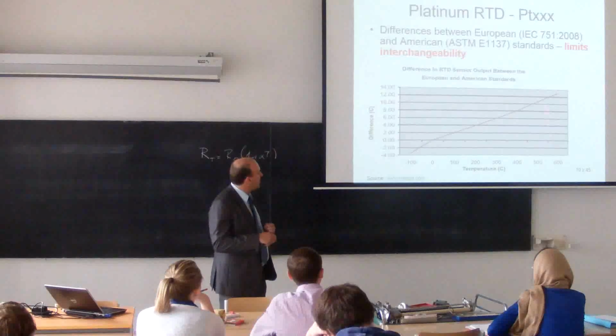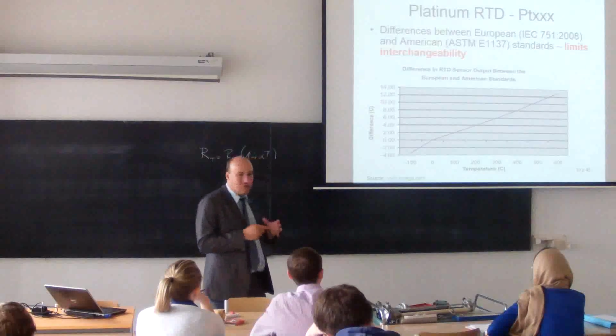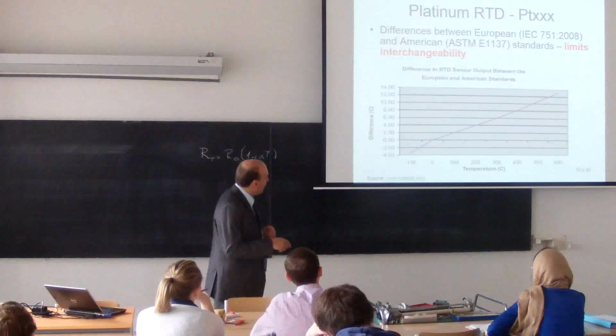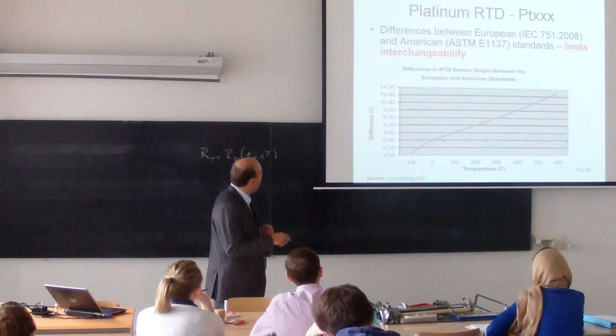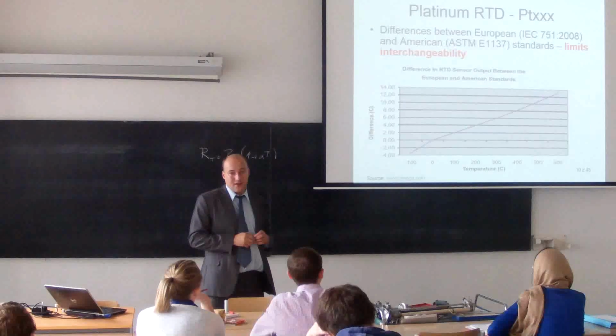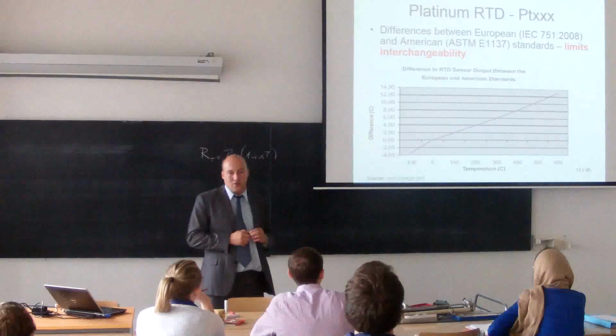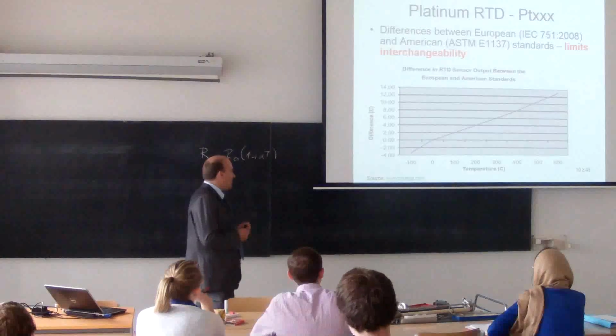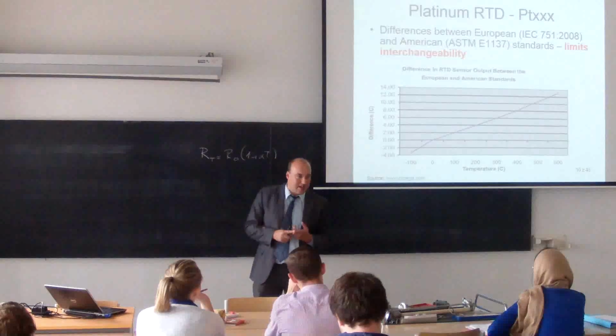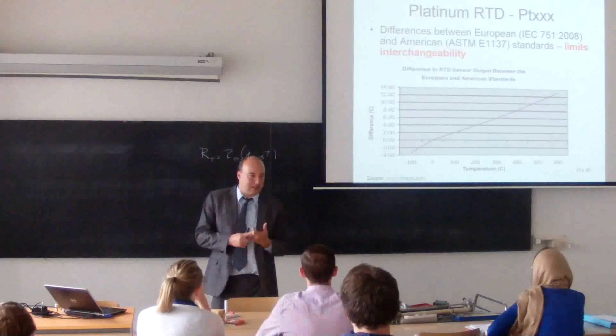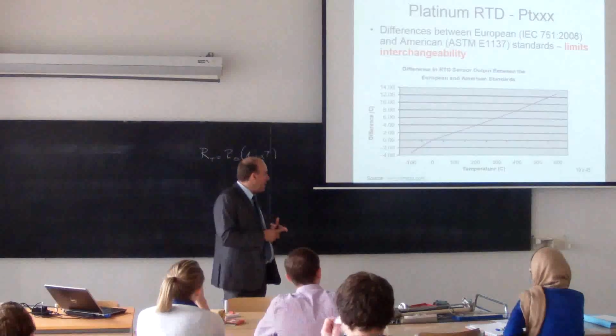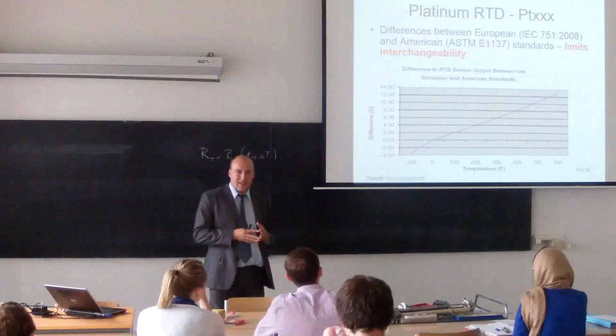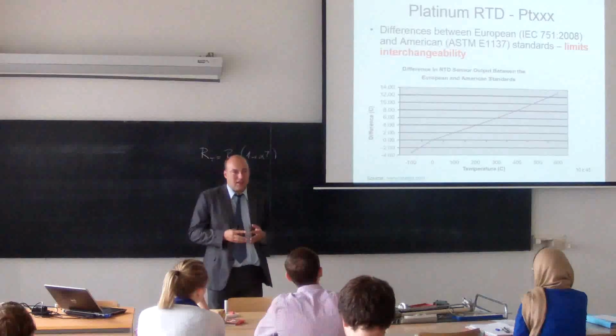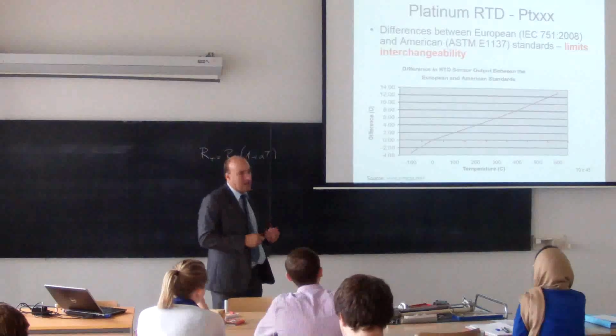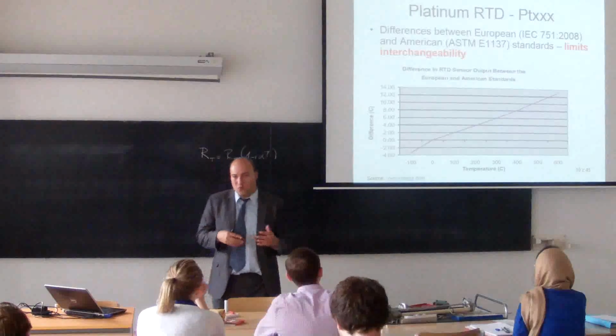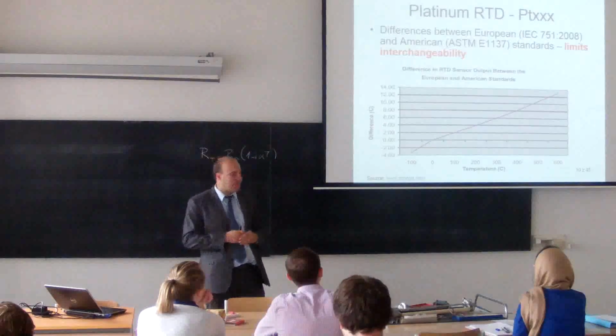For higher temperatures, it's even worse. Let's imagine I want to measure something really precisely at 500 centigrade, somewhere here, and I have about 9 centigrade error. That's quite a huge error. So when you use this kind of sensor, it's not only important to know what type of sensor you want to buy, but also what standard is used in your application. I don't think it really matters which standard you use, but you have to use the same one if you don't want to recalibrate your application.